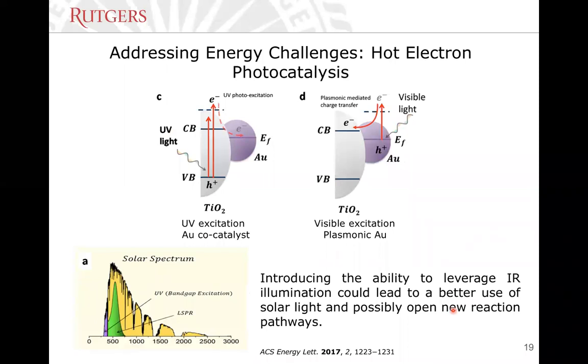And the other way, as I was telling you, to make nanoparticles do things, normally, the primary way is to excite in the UV, where you have microscale TiO2 particles, microparticles or bulk TiO2 decorated with small gold nanoparticles. These are about a few nanometers. We are not interested in plasmonic behavior in these nanoparticles, but rather in their surface defects. So in this case, the TiO2 absorbs UV radiation. Then these electrons, the conduction band electrons, are transferred into the small nanoparticles, and that's where the reaction occurs at the surface.